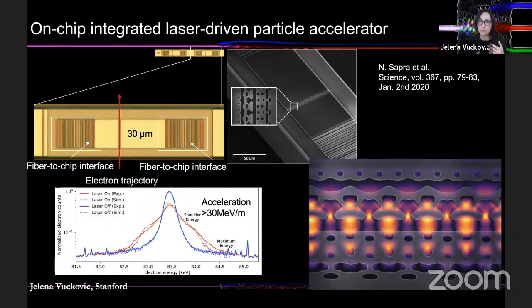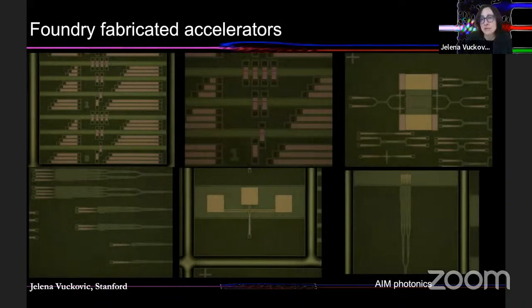Like in a traditional accelerator, you need hundreds or thousands of stages to really achieve the target energy, which tells you that within an inch or a couple of inches of a silicon chip, we can really go from 80 kilo electron volts, which is the initial energy of electrons we have here, to about the mega electron volt range for the existing structure, which is already very interesting and exciting for radiation therapy or some material science or imaging applications. And that's what we're trying to do now, integrating hundreds or thousands of these elements on the same single chip. And we don't want to do that by hand in a nanofabrication facility, but instead we're working with commercial foundries on building this on-chip accelerator. So that was the explanation of what we're doing.